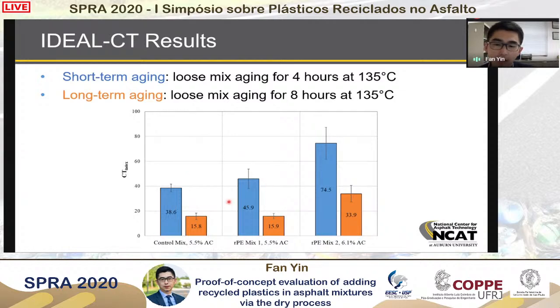The second one is the plastics without changing the binder content. And then the one on the right side is a plastic modified mix at higher binder content. So very interestingly, from this data, we can tell that the two mixes on the left side did not show much difference at both aging conditions. But the one at higher binder content gave us a much higher CT index, which indicates better cracking or durability